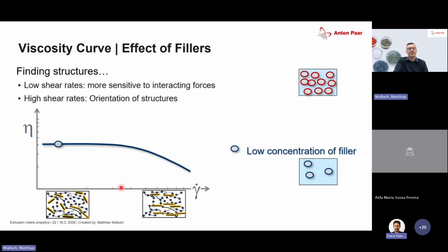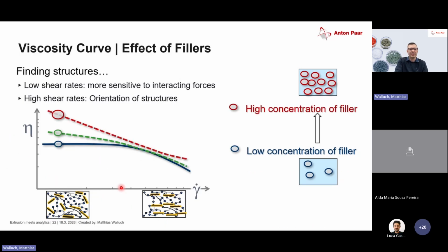We can also get information about the filler content of materials. Here we can see a standard curve of an unfilled material, and now we increase the filler content. And as we can see, with an increased filler content, we also increase the zero shear plateau. If we have a very, very high filler content, it might be that the viscosity just keeps increasing without any plateau in the end, which is not measurable anymore. This is just because we have interaction between the molecules, which are then breaking up when I apply a higher shear rate.